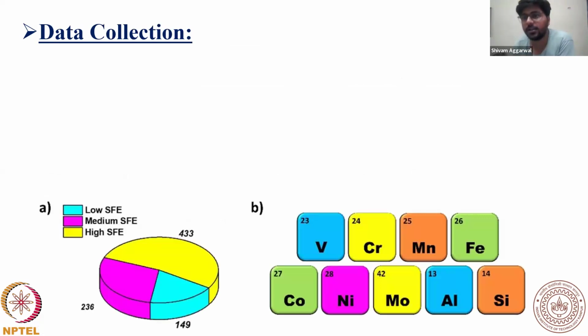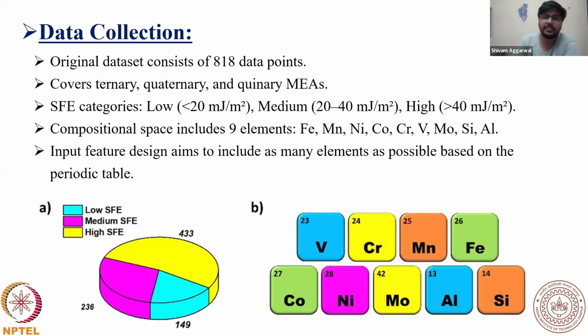So, data collection. In this work, the original data set consists of 818 data points, and this covers ternary, quaternary, and quinary medium entropy alloys. This data has a very wide range of stacking fault energy, from very low, below 20 millijoule per meter square, to very high, greater than 40 millijoule per meter square. And in this data, we are using 9 elements: iron, manganese, nickel, cobalt, chromium, vanadium, molybdenum, silicon, and aluminium.